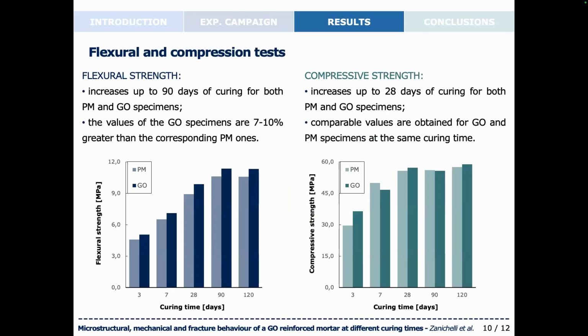Relatively to the mechanical tests, here are shown the results in terms of flexural strength and compressive strength. On the left, we have the flexural strength that increases up to 90 days of curing for both PM specimens and GO specimens, and then it remains stable up to 120 days of curing for both of them, with higher values for each curing time registered for the GO specimens.